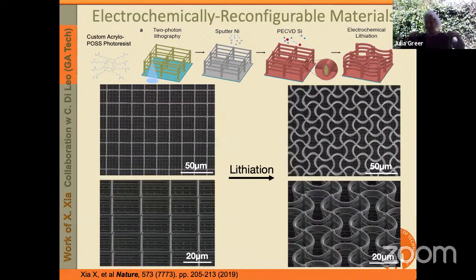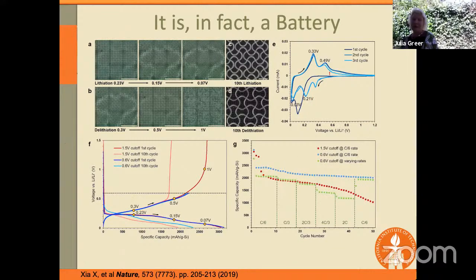And so here's the top view before and after the lithiation, as well as the tilted view. And so you can start seeing these nodes, right? You can see that the beams around the node co-rotate to create this kind of a shape. Now, I'm not showing this to impress you with a cool pattern. What I'm showing you is that it's truly a battery. And in fact, when you lithiate and delithiate, you can see that the pattern that's formed either buckles very closely together or then it unbuckles farther away from one another.